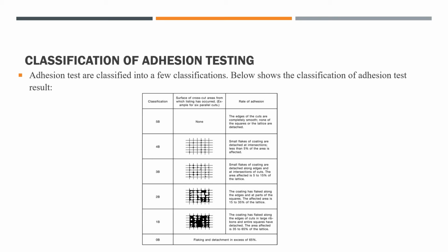At 3B, small flakes of coating are detached along edges and at intersections of cuts. The area affected is 5 to 15% of the lattice. At 2B level, the coating has flaked along the edges and at parts of the squares. The affected area is 15 to 35% of the lattice. At 1B level, the coating has flaked along the edges of cuts in large ribbons and entire squares have detached. The area affected is 35 to 65% of the lattice, and at the level of 0B, flaking and detachment is in excess of 65%, which will result in failure.